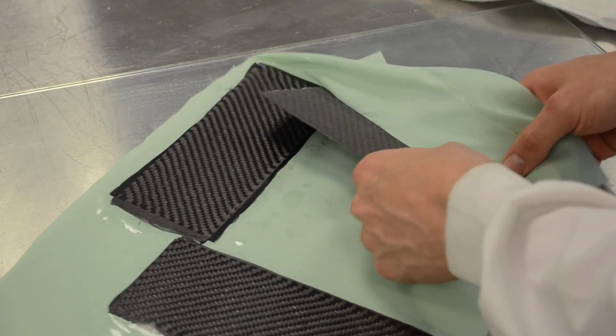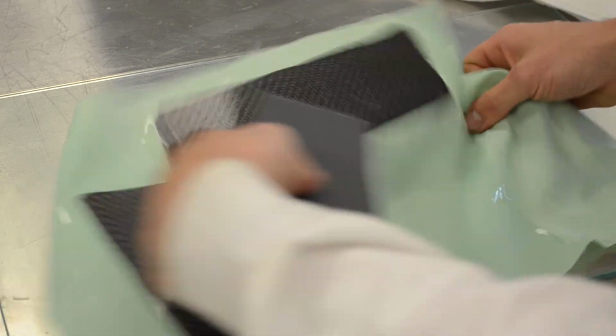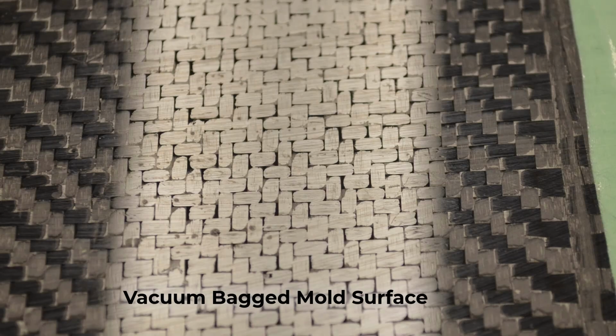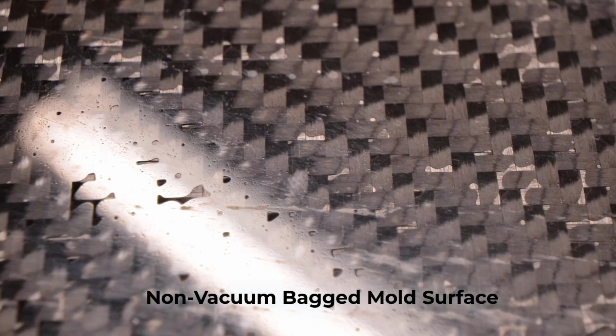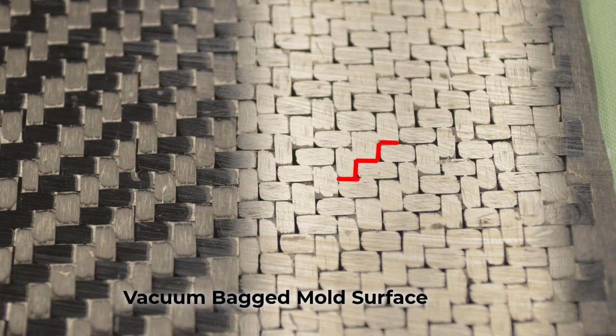Now that we have produced and post-cured all of our samples, there are a few ways that we can assess their quality. Observing the surface finish on the mold side, both the vacuum-bagged and non-vacuum-bagged samples have surfaces which may be considered defective depending on the application. The non-vacuum-bagged samples entrapped a considerable amount of air which produced small areas where the resin does not follow the mold surface. Over the entire surface of the vacuum-bagged sample, the surface areas between the tows are not filled with resin, producing a slightly patterned surface.